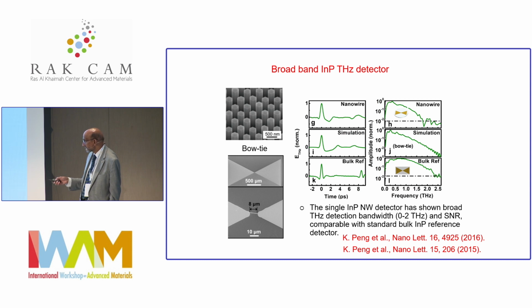You can see the electric field as a function of time here, of the nanowire detector, and in the simulations, it's what you would expect. On the bulk reference, they're very much comparable. If you take the fast Fourier transform of this one, you can see the frequency domain. You can create these broad bandwidth nanowire terahertz detectors. That means you can pack multiple devices for high resolution biomedical imaging applications. That's what we're interested in, and we spent a lot of time making these things work. And also these are operating at room temperature.